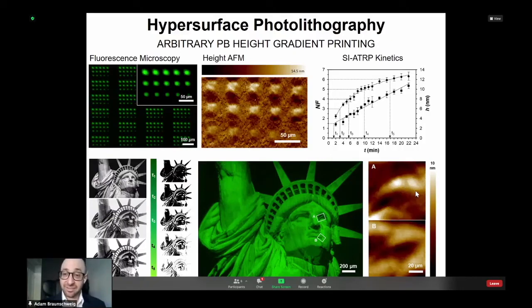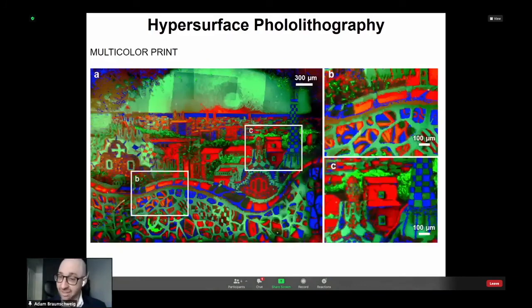And then here you see the AFM of the eyelid and the lip, just further confirming that we are able to precisely control the heights of the polymers in each of the 750,000 different pixels. So what about controlling both the height and the composition of each polymer? This would be incredibly complicated in any other printer. What we have here are 3 different polymers and 4 different heights of each polymer. So you could possibly do this using 12 different photomasks, but we could do it in just approximately an hour, and that time is really dictated by the kinetics of the polymerization.